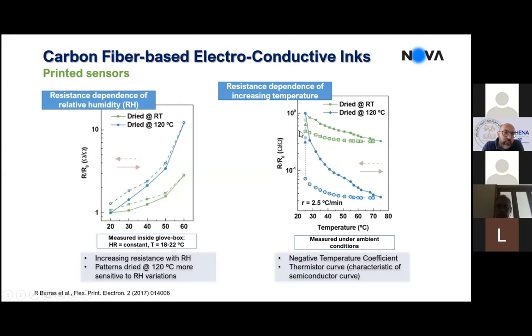The good thing about these sensors, they are also sensitive to temperature. Why? Because the carbon fibers behave like a semiconductor, and then you have the decrease in the resistance with temperature. And they respond differently to the temperature when you compare with humidity. So they are sensitive to both, but they respond differently.